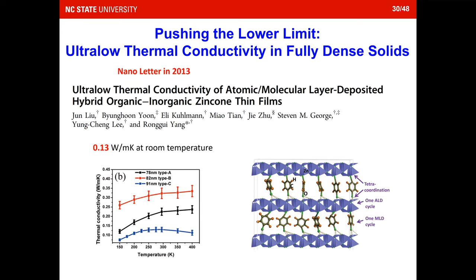Can I add some disorders in between? So I work with the professors in chemistry. We add some molecular chains, layers in between. Hopefully that can provide enough disorders, but it turns out the disorder is not enough. So what we get as the lowest thermal conductivity is 0.13, which is already pretty low, but still cannot beat